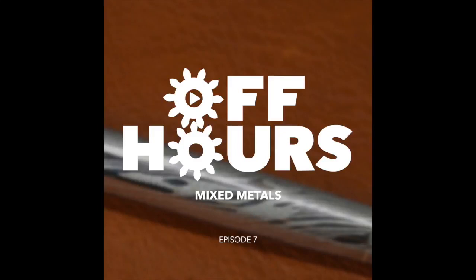Or you can go for longer, you could go for 20 or 30 minutes, and you'd actually get quite a deep etch out of it. And that gets you quite deep into it. Actually, I should say that it's attacking the 304 stainless, not the 316. Muriatic acid doesn't attack it.